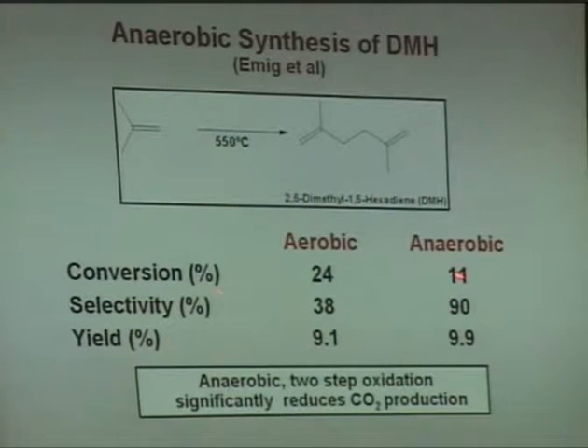The conversion drops in half, but the selectivity goes from 38 to 90%. Huge difference in selectivity, coming out with actually an overall yield in the process that's higher. Conversion is low, but the big difference in selectivity makes up for it. So this is a wonderful example, once again, of showing what happens if you take the oxygen out of the process. You can reduce CO2 emissions very significantly.